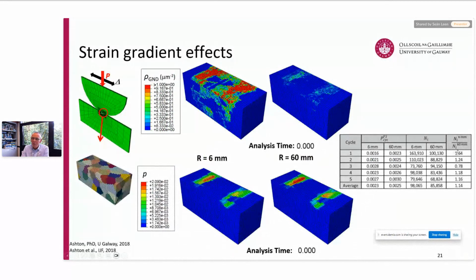And if you look at the table on the right-hand side, you can see that the lives in general for the smaller contact are larger, except for one exception. So there's a statistical effect here as well. They're generally larger than the 60 millimeter case. But this was kind of, if you like, a quick look-see.